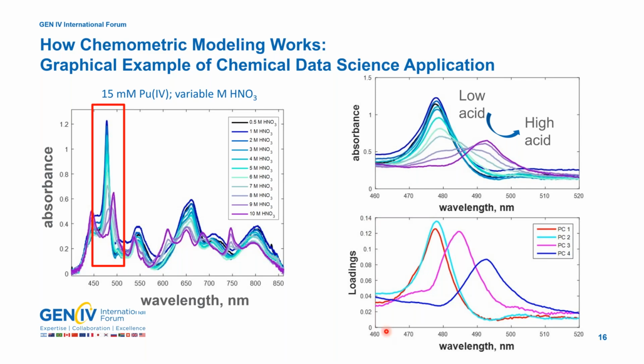So we're looking at these loadings as a function of wavelengths, and this is the same wavelength range as we see up here. Let's just give a quick example. If we look at the wavelength range of 510 to 520 nanometers, we see that this is pretty flat. We probably wouldn't really rely on this too much for quantifying plutonium-4 if we were making the decision. And if we look at how our model's looking at that same region down here, it's giving it very low loading, very near to 0. So our model agrees with us. This isn't too important for quantification.